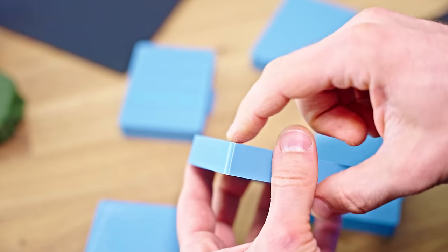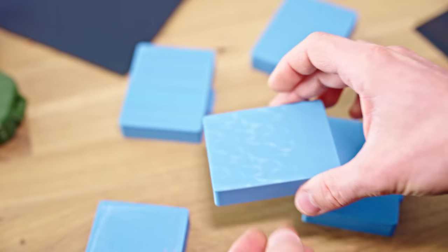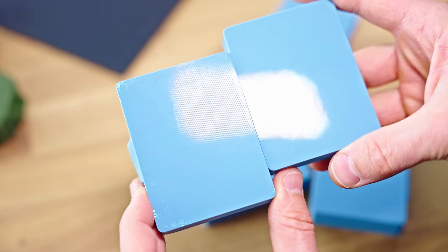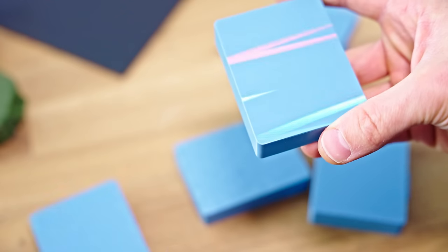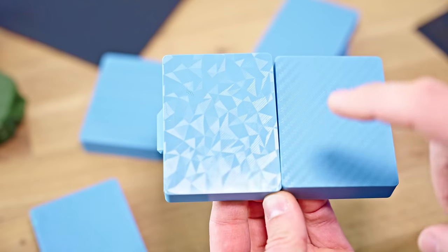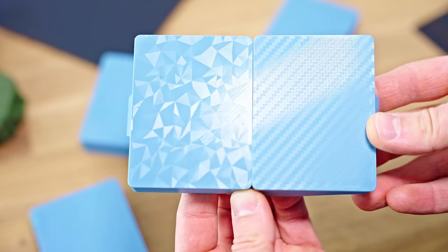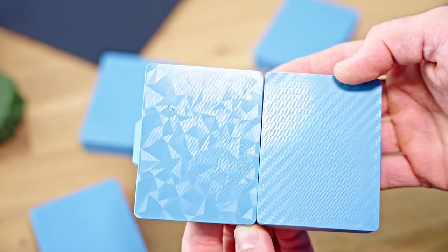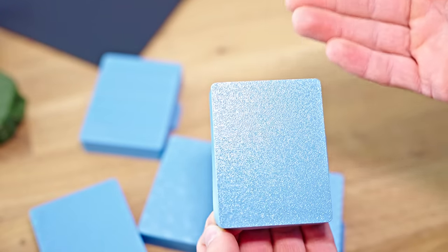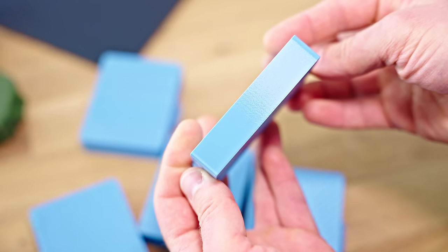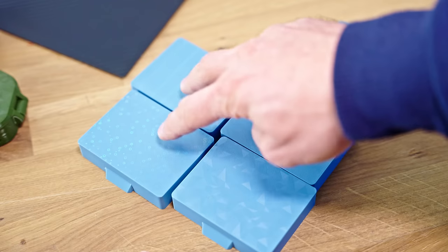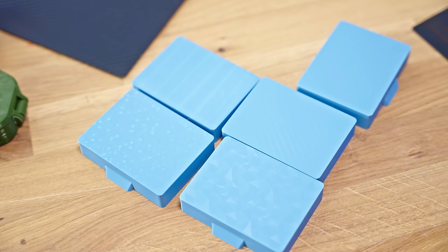So how did the PETG prints fare on these surfaces? These are all vase-mode, very thin, but quite challenging to print because there's a sharp edge right there. And this is quite the mixed bag. The two holographic surfaces have quite the amount of corner lift, you can see it right there catching the light, right at the corners, these do stick up quite a bit. Polygon and the carbon fiber textures, they do have just the tiniest amount of corner lift at the edges, but nothing that is really worrying. And then the one that I did on the textured PEI, this one's essentially perfect, but it's also quite hard to tell whether these have lifted. I don't think they did, they look very flat. But yeah, overall the two novelty holographic ones do look quite a bit worse than just ones with texture.